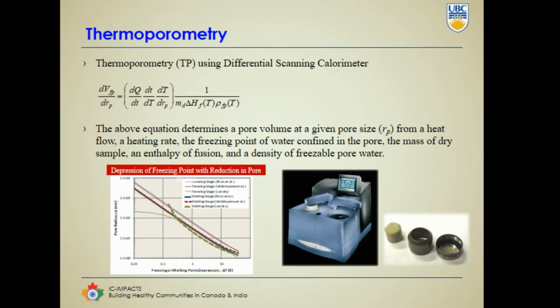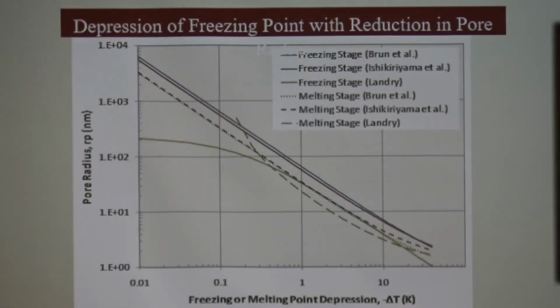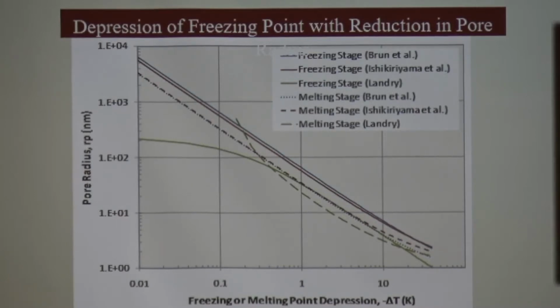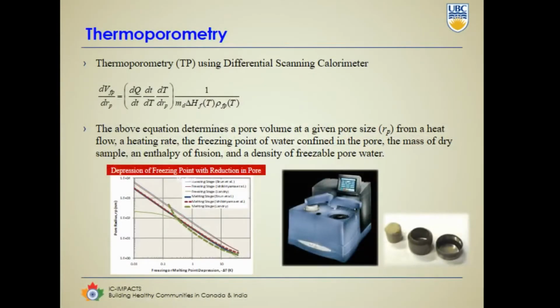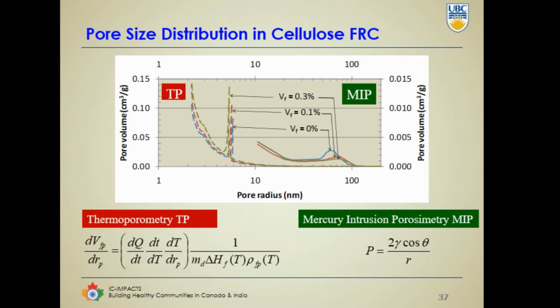So in thermoporometry, we freeze the system, and the greater the depression in the freezing point, I know there has been a reduction in the pore diameter, which is what we call pore refinement. And I like that because the smaller the average pore diameter, the more resistant the material is to ingress of deleterious agents, right? So I want this to be a non-permeable system which doesn't allow any deleterious agents to go through. And what you will notice is very interesting. Here are the mercury intrusion porosimetry tests, and these are our thermoporometry tests.